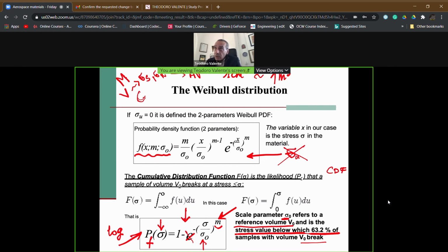Decreasing the resistance of the engineering component means that if you increase the volume, it is going to increase the probability of failure of the component itself for the same external applied load. Again, it is a tensile load. So we cannot skip the volume effect in the design phase, and this is a big difference with respect to the metallic alloys. Why? The reason is very simple.